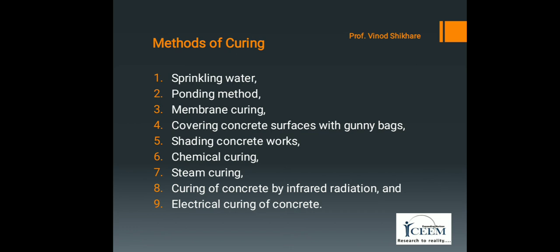The last method is electrical curing of concrete. This method is not used in India as it is more expensive. It is mostly used in very cold climatic regions. Passing alternating current of low voltage and high amperage through electrodes in the form of plates covering the entire area can cure concrete products. The potential difference generally adopted is between 30 and 60 volts.